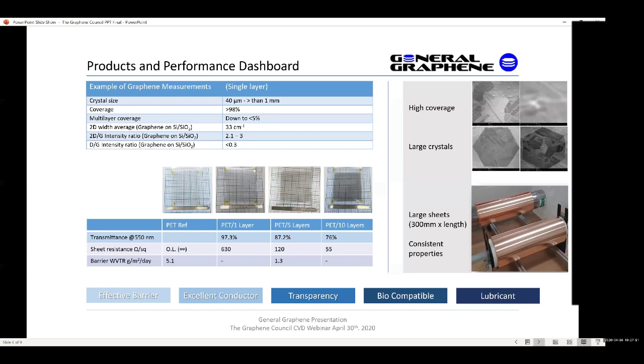So moving to the lower part of the table, the optical transmittance of monolayer graphene is about 97.3%. With 5 layers, the optical transmittance remains typically 87.3%, and even 10 layers of graphene offers an optical transmittance of 76%. Typically, monolayer graphene offers a resistivity of 630 ohms per square. Multi-layer graphene, however, offers a resistivity as low as 50 ohms per square, and when properly doped, the literature supports a resistivity of less than 25 ohms per square.